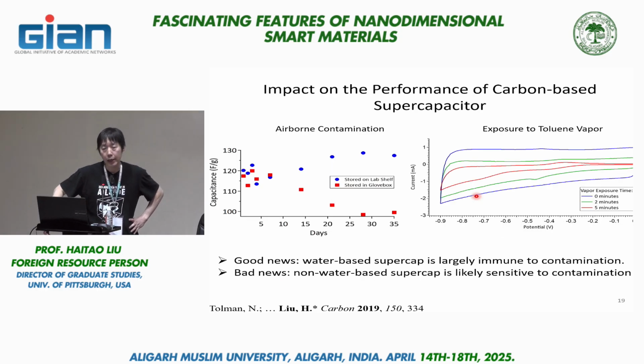What people actually use are active charcoal, active carbon, porous carbon materials. Those are the ones actually being used in making supercaps. Now those materials have very different surface chemistry. They have a lot of oxygen functional groups because of the way they are made. Okay, they're a lot more porous, so there's higher surface area. And we find those materials behave very differently.